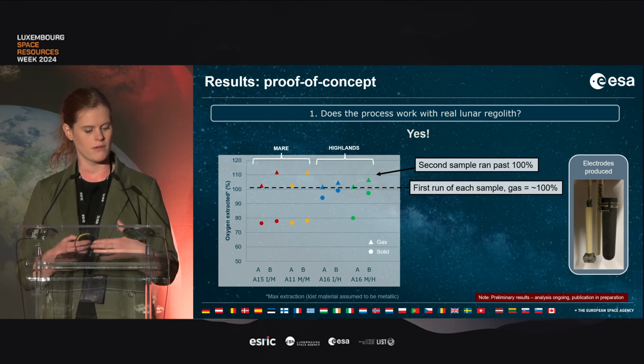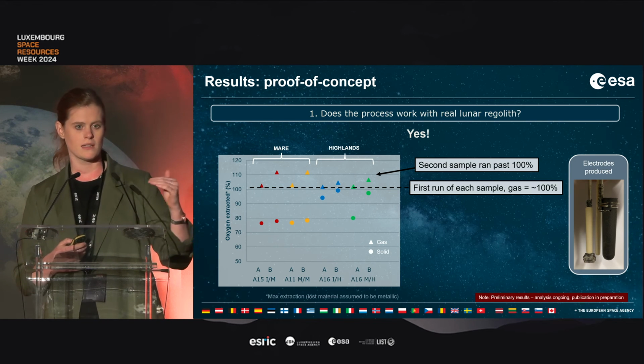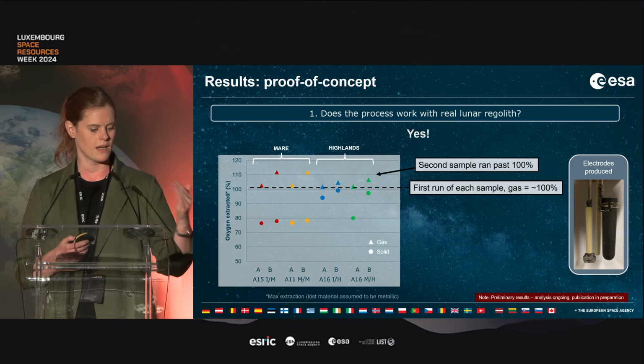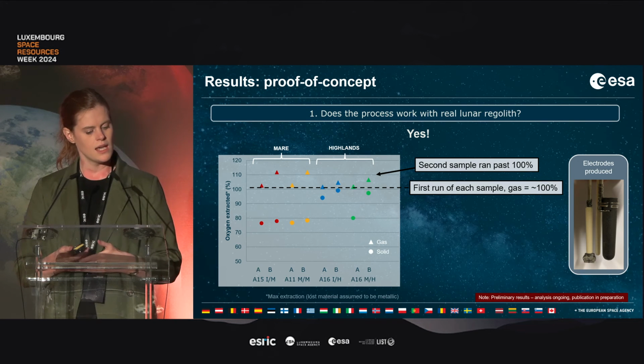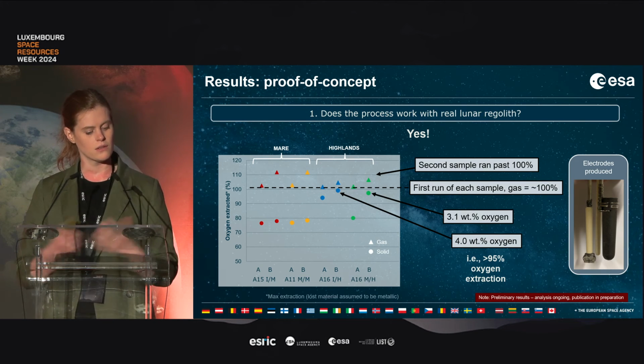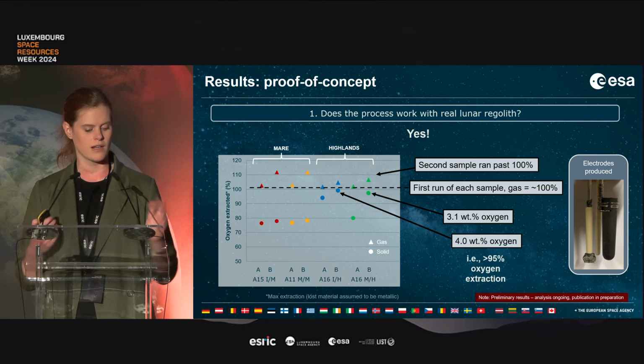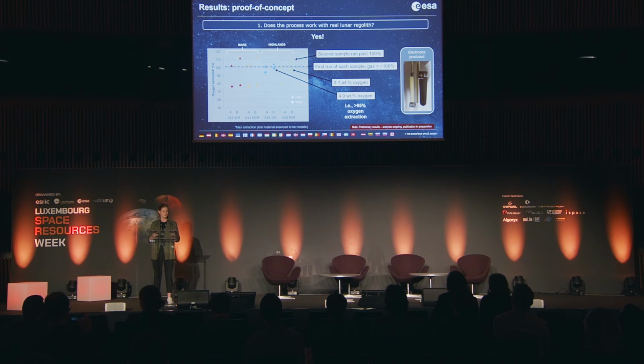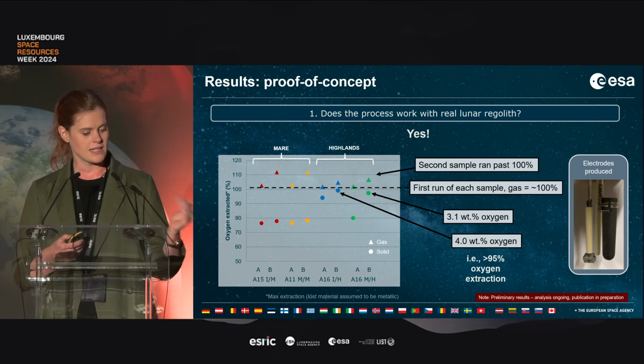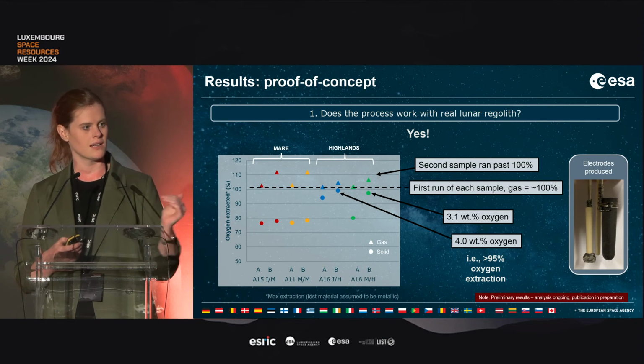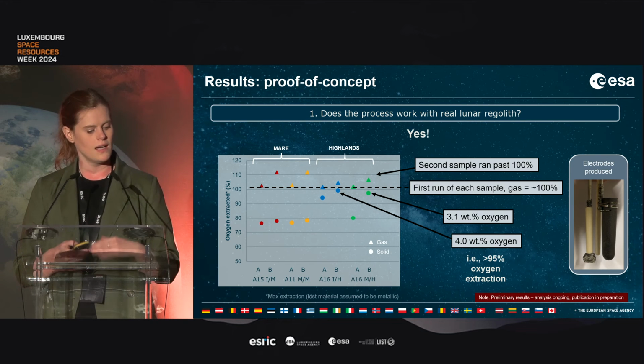So for the second experiment, we ran a bit past 100%, with the delta determining how far we overran on the second run. And here we got the 2 Highland samples down to around 3 and 4 weight% oxygen, respectively. So that equates to over 95% oxygen extraction corroborated between the gas data and the solid product analysis. From that we can say that the process does work with real material. However, we can see that clearly there's a difference between the Highland and the Mare behaviour.